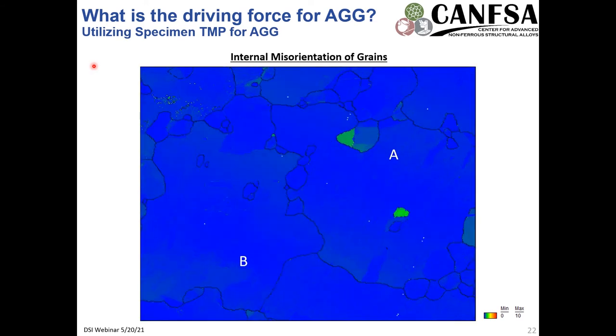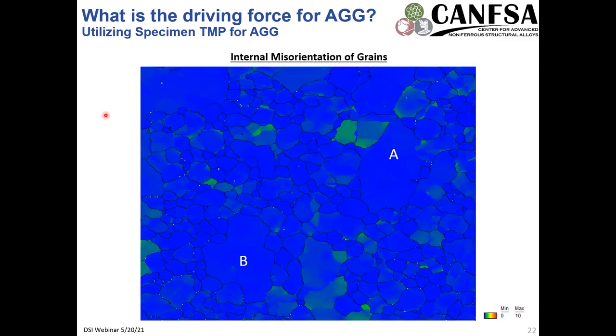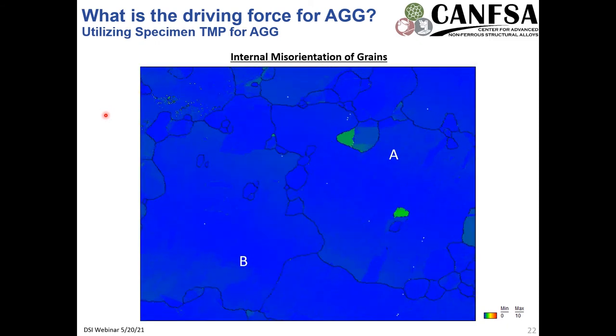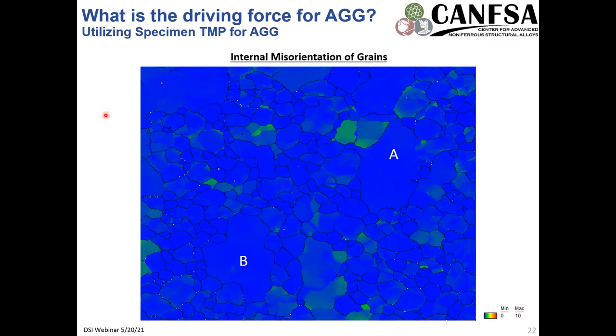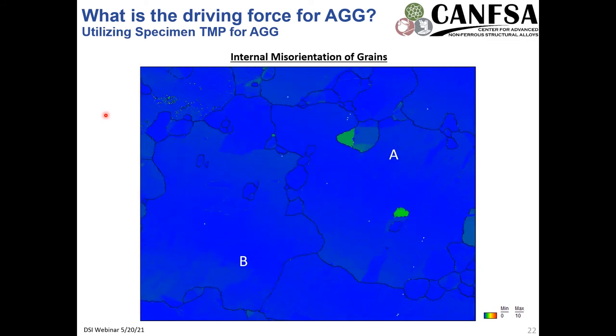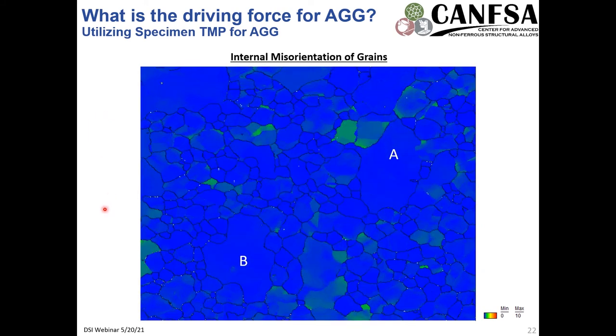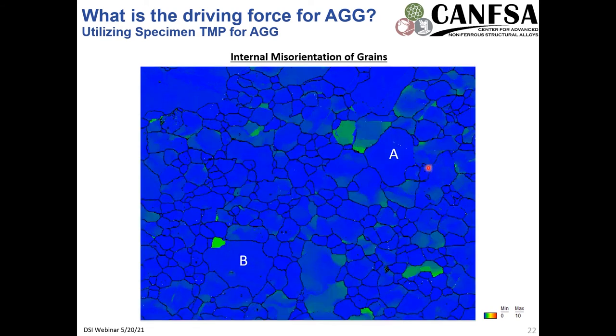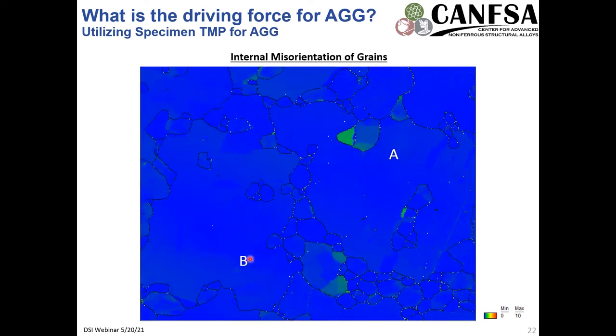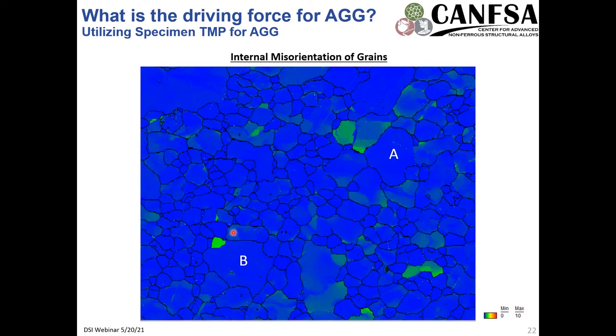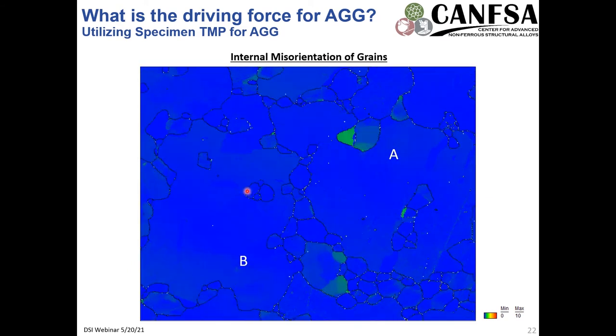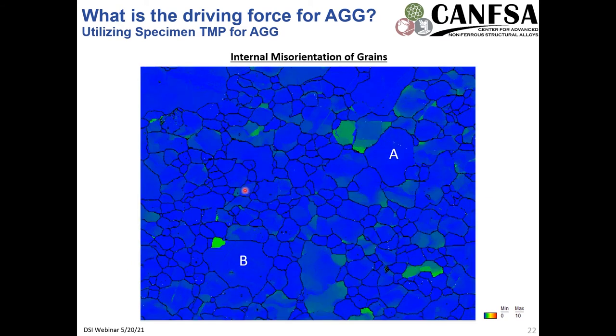And so here it's progressing through the as-deformed state and 1110, 1130, 1150, and 1170 Celsius to track the abnormal grain growth that's occurring. We have grains A and B here that grow to consume neighboring grains. And you have these island grains that are within the material, but those are eventually consumed at higher temperatures.